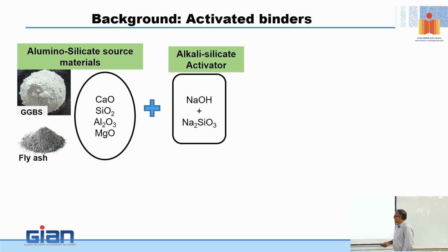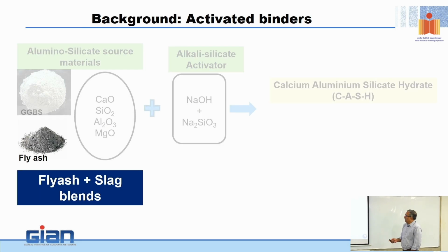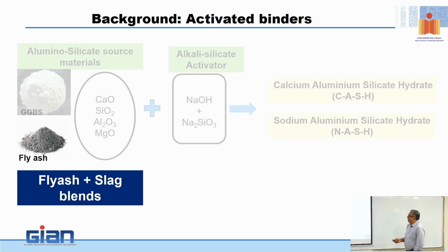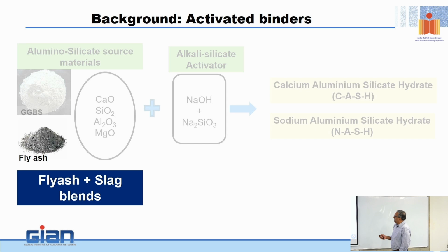Now, what is the outcome of this process? If I use either a fly ash or a slag, I would form one of these two binders: calcium aluminosilicate hydrate or sodium aluminosilicate hydrate. It's not really a hydrate, it's a misnomer. But somehow the name NASH has stuck because of a fortunate or unfortunate accident that happened in a committee, and that name has since persisted. At the outset, I want to clarify one thing. People use the term geopolymers rather loosely. Geopolymers, by the strictest definition, are these sodium aluminosilicates.